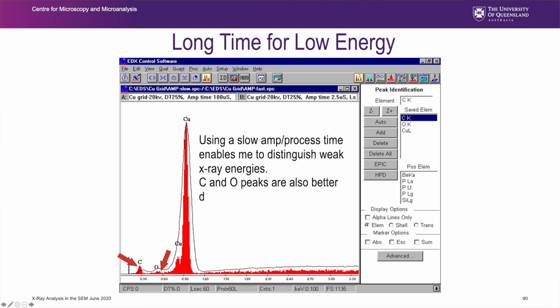I can also see in red a better carbon peak and a better oxygen peak. Really, the carbon's contamination and the oxygen is surface oxidation, but I can pick it up better. Why? Because the peaks aren't smeared out as much.